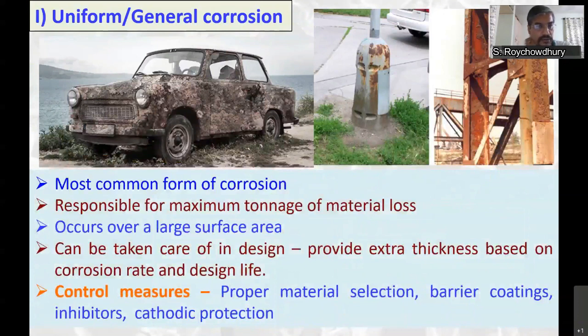So first is uniform corrosion. These are some typical images which you commonly see. You can see the corrosion products. It's the most common form of corrosion. This form is responsible for the maximum tonnage of material loss, which occurs over a large surface area, and it can be easily taken care of by design, by providing an additional corrosion allowance. Control measures: proper material selection, barrier coatings, inhibitors, cathodic protection. They will help in minimizing uniform corrosion.